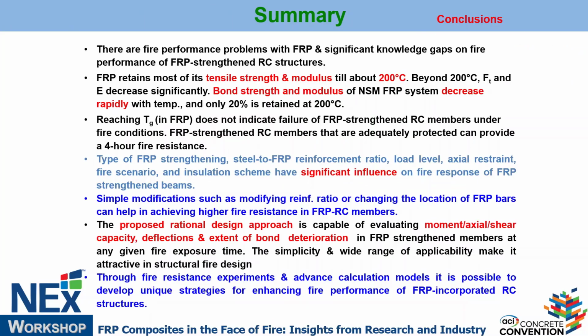So finally, it can be addressed. This is not a big science or anything. A fire problem can be easily addressed, but it needs a lot of material level data as well as some validation test data, which are expensive, under fire exposure. Now, FRP up to 200 to 250 degrees centigrade is no big deal. You can manage. But beyond that, it loses strength much faster, rapidly, as opposed to steel, where up to 400 there are not many issues. Now, reaching Tg does not mean it's failure, which some people say, that after Tg is reached, it is neglected. It's not. It's still contributing to some extent.